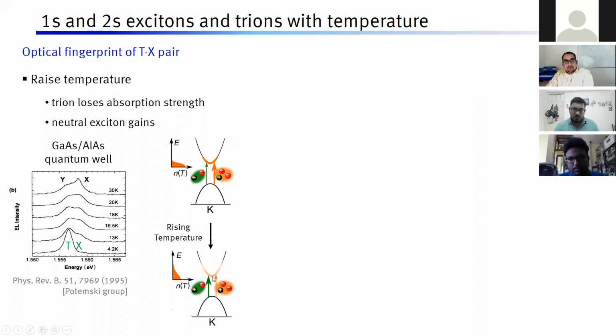However, when you raise the temperature, you have this Fermi-Dirac redistribution of electrons within this band. So then you create some empty states here, right? So you can create more excitons now and fewer trions. This is the only thing. This is the transfer of oscillator strengths. But it is only valid for a doped sample. For an undoped sample, it will not happen, because you will not have trions at all.